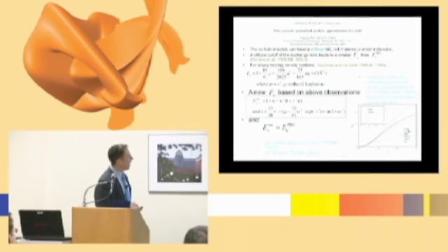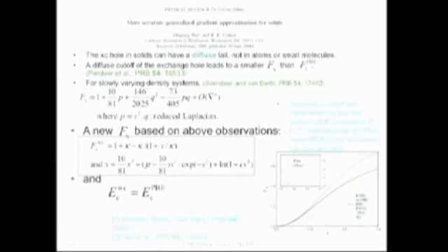So we looked at the regular GGA, and I mentioned it has this exchange enhancement factor. We wanted to find basically a different exchange enhancement factor than in the PBE. This was actually work of Zhigang Wu, who's now a professor at Colorado School of Mines. He was a postdoc with me at the time. What we noticed is that the PBE GGA didn't work very well in diffuse systems. It didn't treat the tails of atoms very well.